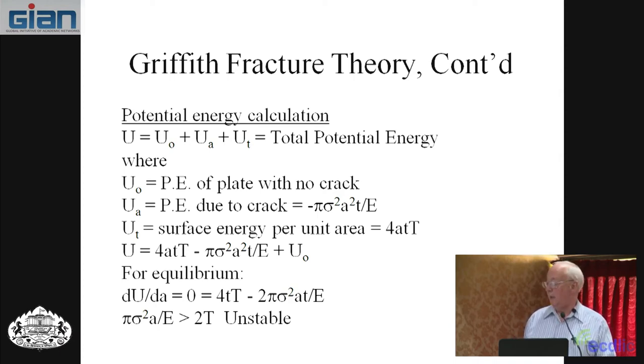Now, if you take advanced mechanics of materials and courses like that, you learn that you can use an energy approach for equilibrium. The energy approach does this: you take the first derivative of the energy with respect to the variable and set it equal to zero, and that gives you the equilibrium position. So the equilibrium position is this. And if you take a second derivative with respect to crack length and get a negative value, then that equilibrium is unstable. Stable equilibrium is like having a ball in a dish. You push it up the side and it rolls back to where it was. Unstable is like having it at the other end of the dish. It's stable on top, you move it away, and it keeps rolling away.